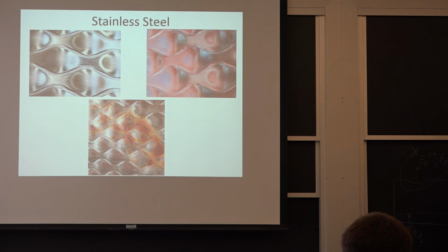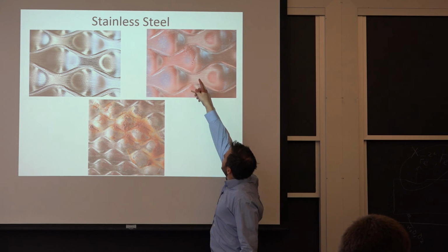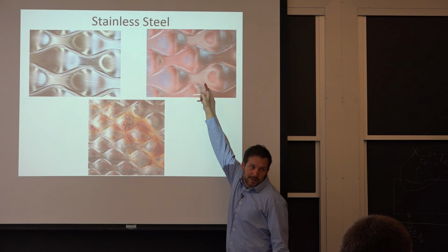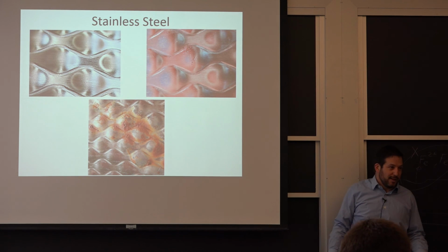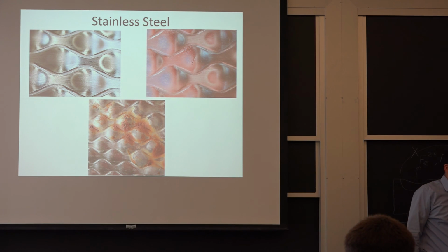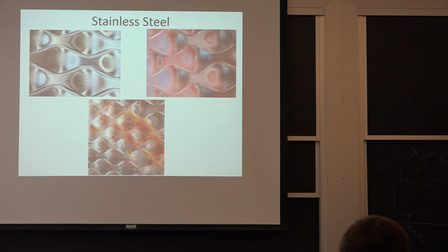And it's very hard to mitigate. That's these images here. You start finding these pits, you see the small holes there? So once it's done, you can try to clean it, polish it. If you still have the holes in there, it's never going to be as resistant as it was in the first place. So it's very, very unfortunate. A lot of people don't really think of this issue, but it does come into play a lot.